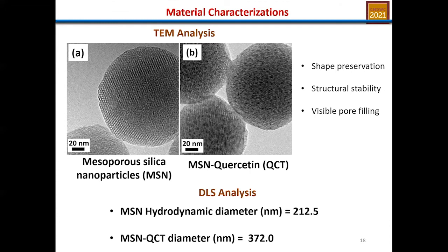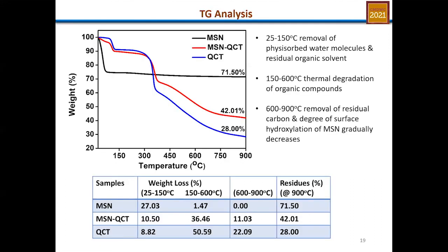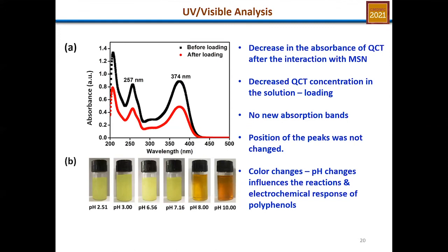From the DLS analysis, the hydrodynamic size increased after loading. From the TGA analysis, at 150 to 600 degrees there was thermal degradation of the organic compounds, such that we found up to about 36.46% loading of the inhibitor in the matrix. From the UV-visible analysis, we also saw a decrease in the absorbance of the quercetin after interaction. There were no new absorption bands formed, meaning there were no negative reactions occurring. Though we observed color changes, these are due to the polyphenols responding to pH changes.